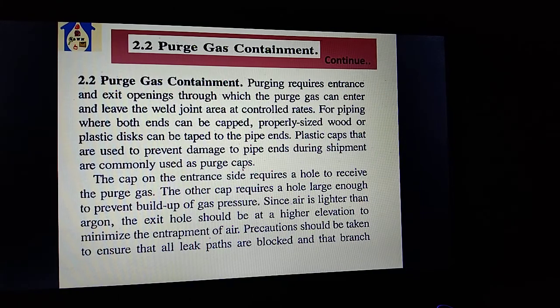The caps can be used on the entrance side, requiring a hole to receive the purge gas. The other cap requires a hole large enough to prevent the buildup of gas pressure. Since air is lighter than argon, the exit hole should be at a higher elevation to minimize the entrapment of air.